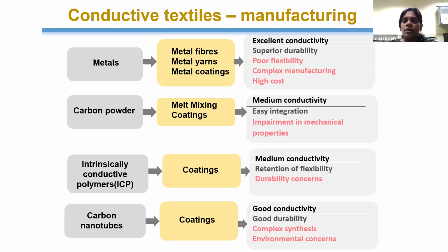These are the application of carbon powder, conducting polymer or carbon nanotubes over the fabric to make it conductive. The carbon powder and carbon nanotubes can be applied over the fabric through melt mixing or through coating. They also impart good conductivity to the fabric. They add negligible weight to the material, so they retain the flexibility. But the problem is that there are environmental concerns with their manufacturing process. So to avoid these issues of carbon powder and carbon nanotubes,